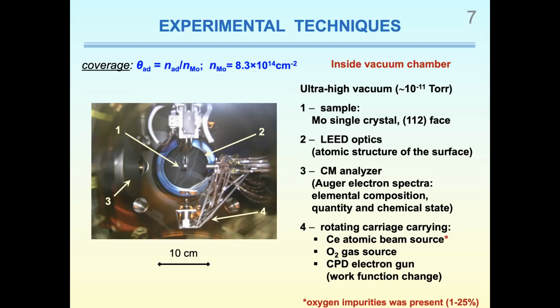Due to extremely high oxidability of cerium, some remnant of cerium oxide could be present in the source. As estimated from joint Auger spectroscopy and LEED measurements, the oxygen part in cerium deposits reached from 1 to 25% in various experiments. Deposition of cerium and measurements were mostly carried out at room temperature.